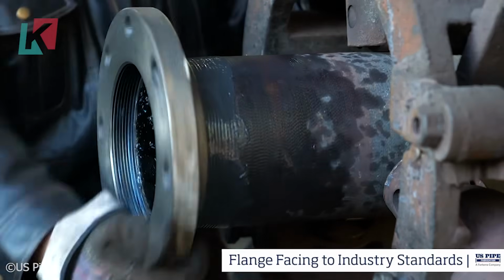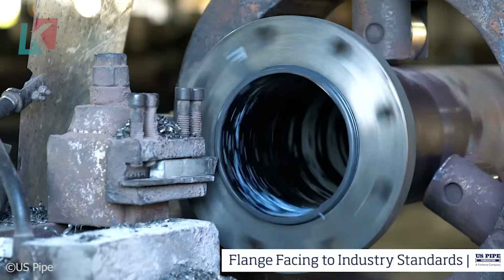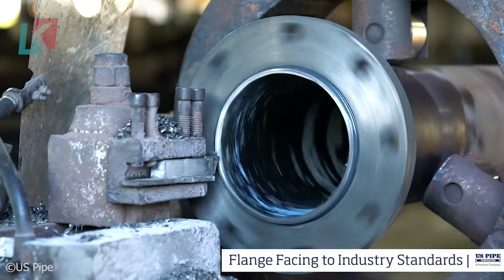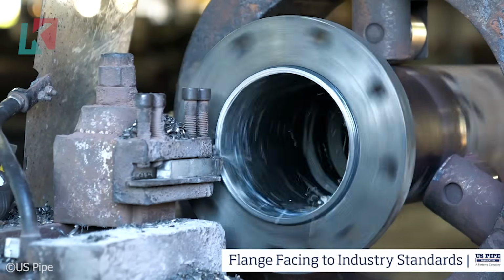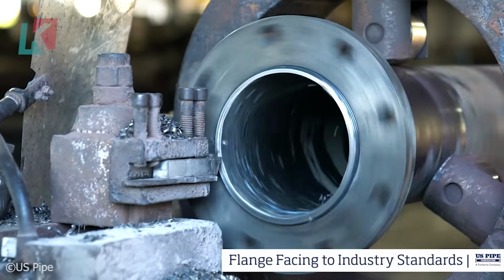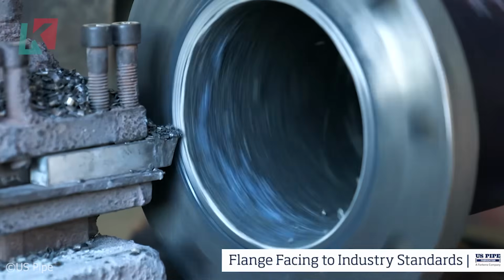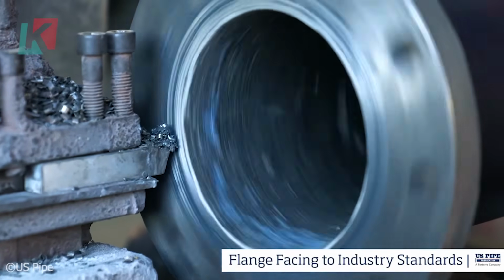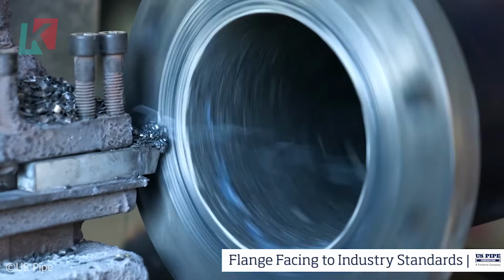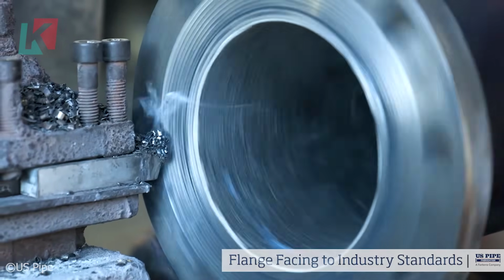We're starting with molten iron at approximately 2,700 degrees Fahrenheit. That's hot enough to melt copper. The iron is carefully treated with magnesium to create the ductile properties that make these pipes incredibly strong yet flexible. Watch this centrifugal casting process. It's like watching controlled chaos become perfect order.